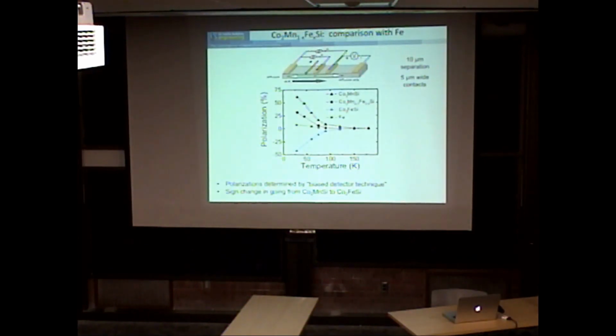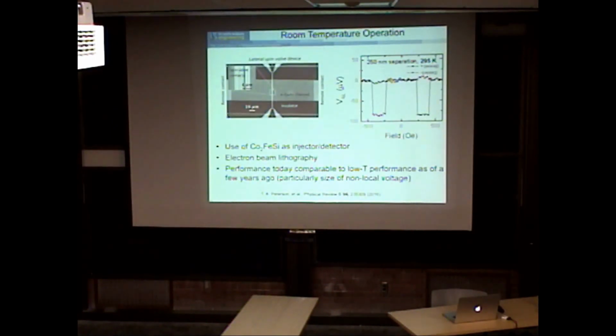Temperature dependence: you go from low temperature up to room temperature, and it looks pretty small, and it's because these devices are big. These are about 10 micron separation. If you make the device small so that the contacts are close, like 250 nanometer separation, this is what Paul's done. We use a cobalt-2 iron silicon injector here. You can get the spin valve signal even at room temperature.